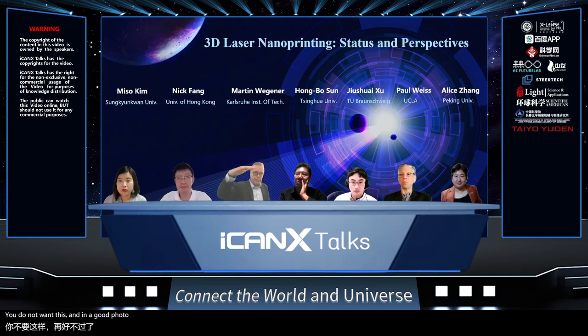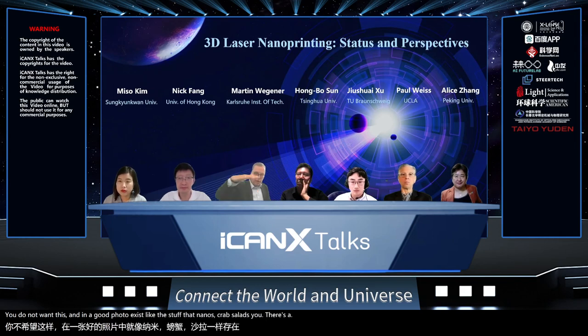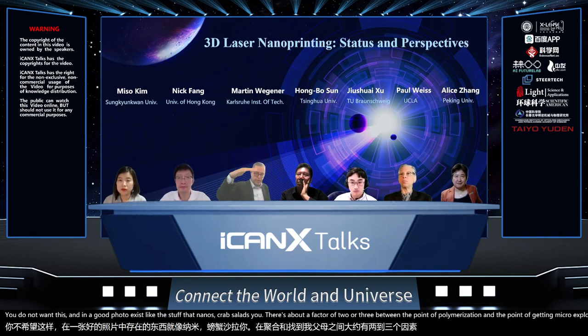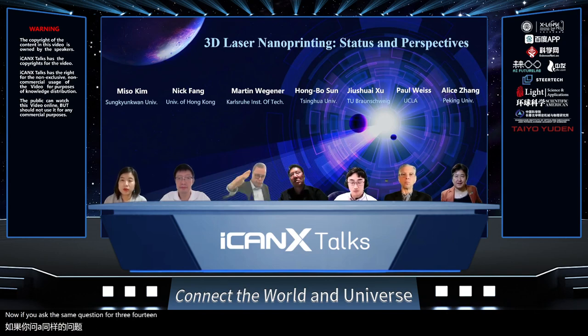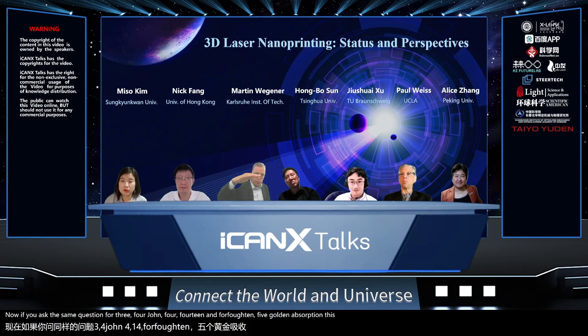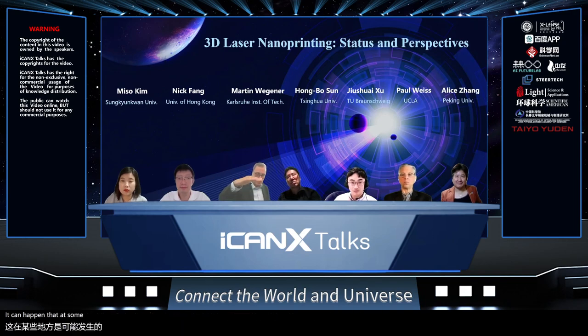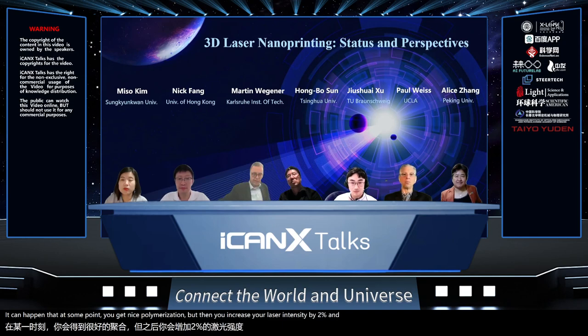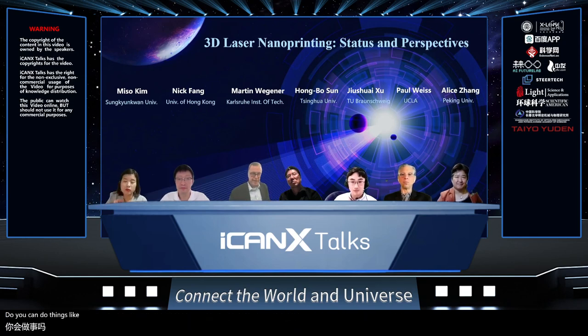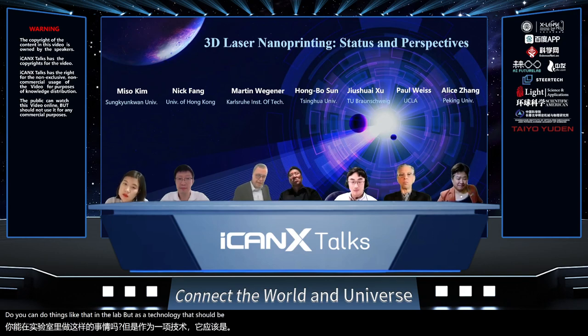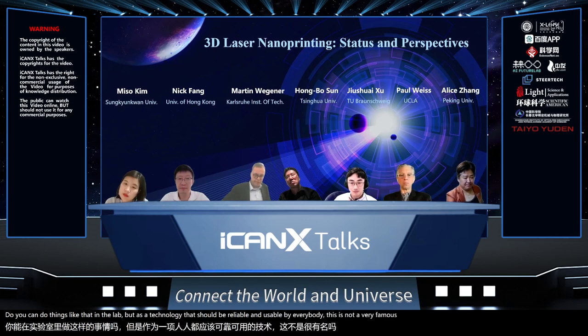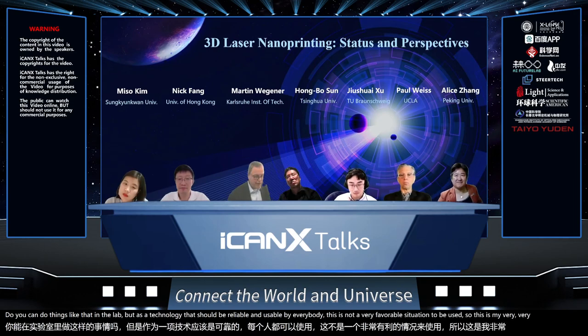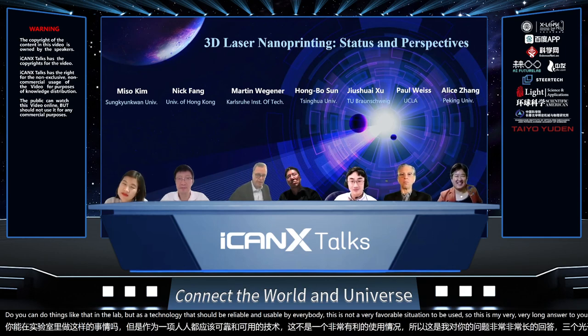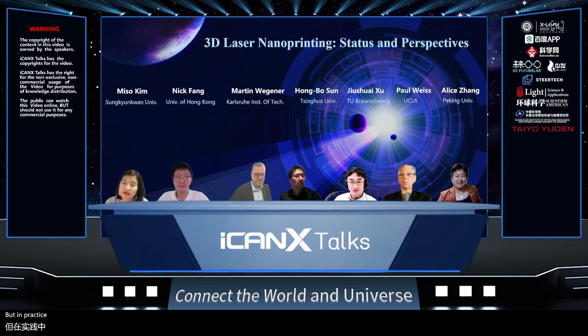And in a good photoresist, like the stuff that Nanoscribe sells you, there's about a factor of two or three between the point of polymerization and the point of getting micro explosions. Now, if you ask the same question for three photon, four photon, and five photon absorption, this window is getting very small. It can happen that at some point you get nice polymerization, but then you increase your laser intensity by 2% and everything explodes. So you can do things like that in the lab, but as a technology that should be reliable and usable by everybody, this is not a very favorable situation. So this is my very long answer to your question. How about three photon and four photon absorption? Yes, in principle very good, but in practice not so good.